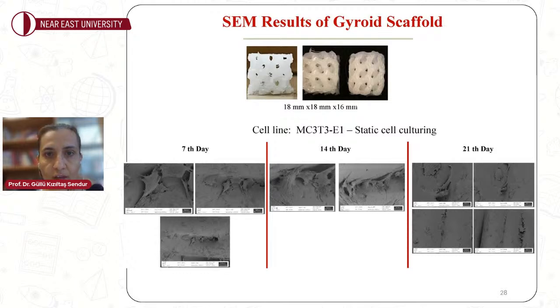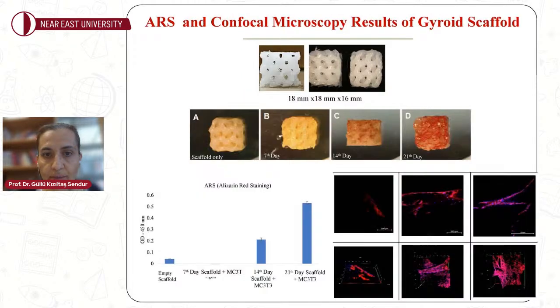SEM results of the gyroid scaffolds that we carried out using MC3T3 mouse fibroblasts were predicting good cell attachment beyond the 7th day, with nice arching of cells over the struts after the 14th day, with the gyroid structure being more favored when you compare it with the uniform FGS structure that I showed you earlier. ARS and confocal microscopy results of the gyroid scaffold were also predicting nice cell attachment and growth within the gyroid scaffold that was a result of our design studies.